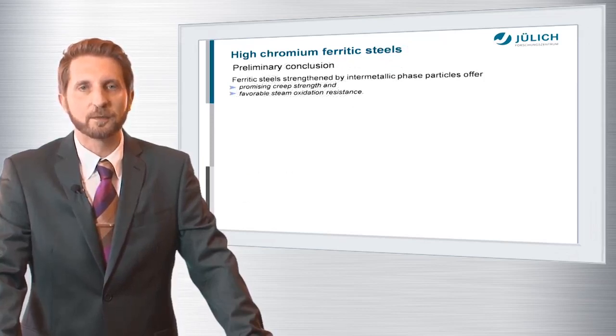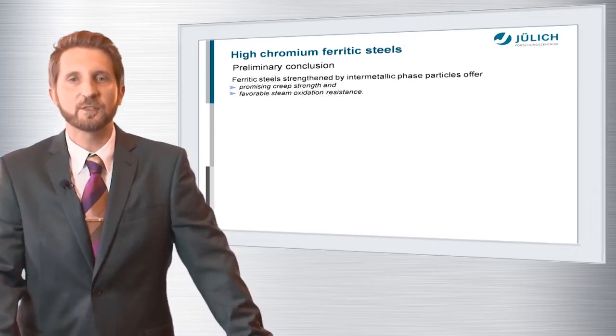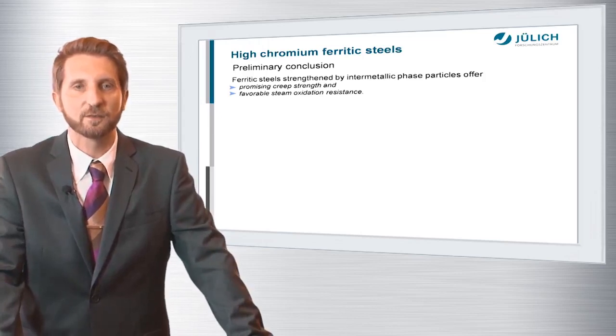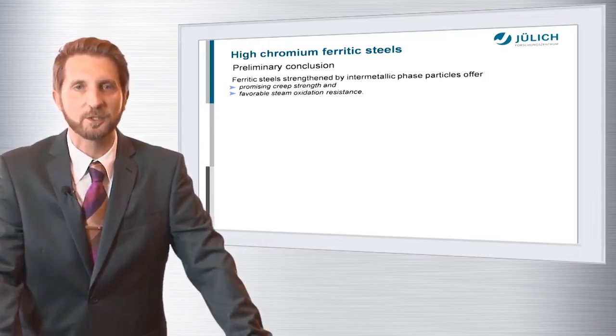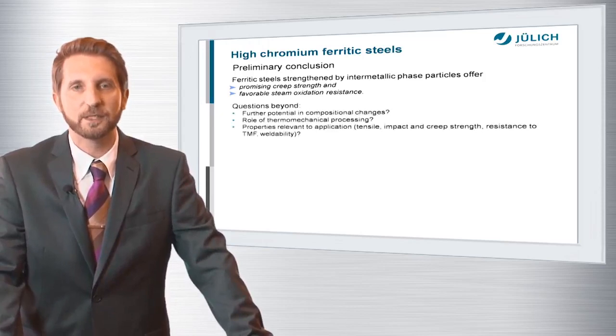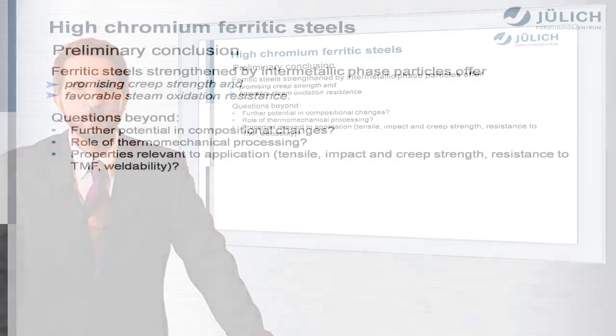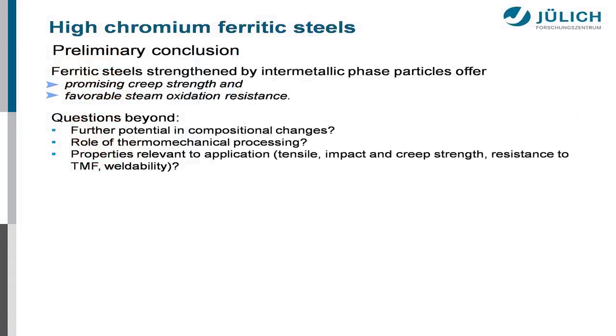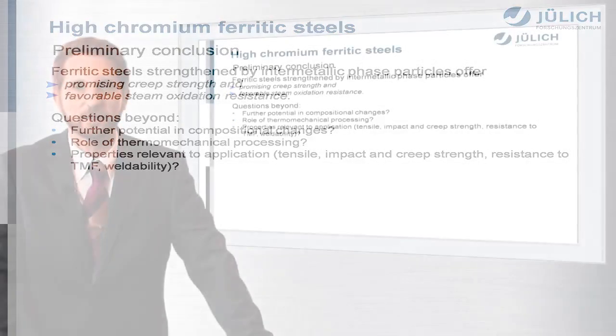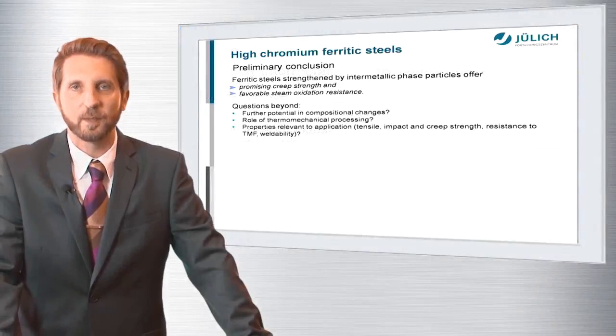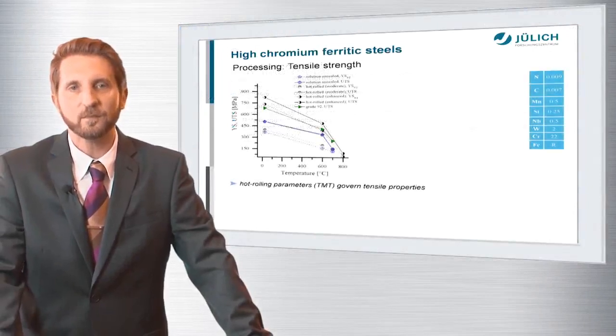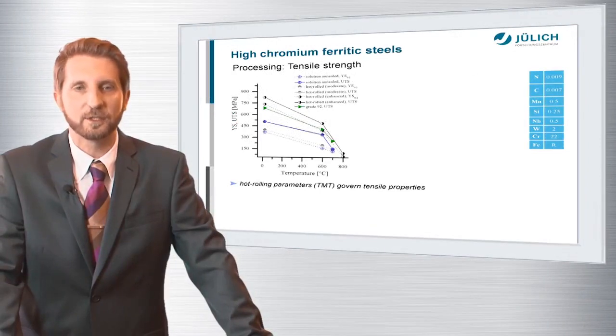So as a preliminary conclusion, we can state that ferritic steels, which are strengthened by intermetallic phase particles, offer promising creep strength and favorable steam oxidation resistance in combination, which is a quite unique thing. But there remain questions beyond. So first question for sure is, what is the further potential in compositional changes? What is the role of thermomechanical controlled processing? And what properties relevant to application can be reached with that? And this is what we concentrated on during the last approximately 2.5 years.